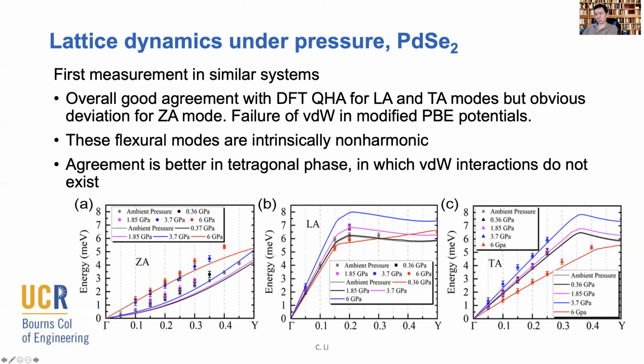And at even higher pressure, after the phase transition, the DFT was able to reproduce it pretty reliably. So a quick conclusion you can come up with is, okay, something is going on when we apply pressure, and something happens at intermediate pressure, well below the phase transition. And the van der Waals bonding behaves more like a covalent bonding once we are up near 3.7 GPa. Additionally, this flexural mode is probably going to be quite anharmonic, because this kind of nonlinear behavior when we apply pressure is not something we would expect in a harmonic or quasi-harmonic system.